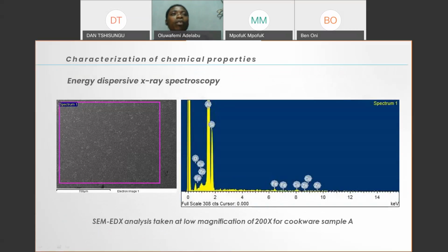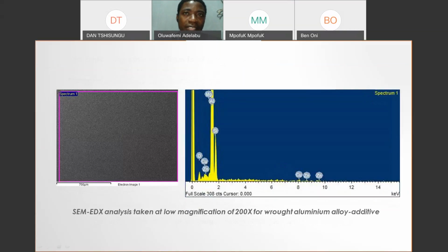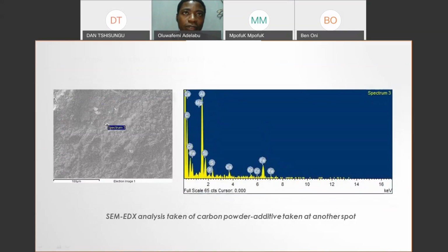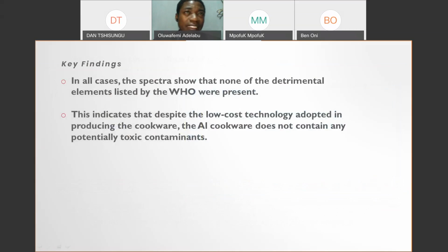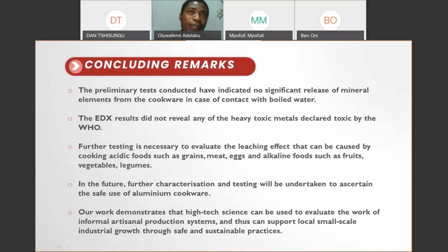All right. So we also did the characterization of chemical properties, and we did that for all the samples. Basically, in all cases, the spectra showed none of the detrimental elements listed by the WHO were present. And so this indicates that despite the low-cost technology adopted in producing the cookware, the aluminum cookware does not contain any potentially toxic contaminant. So our concluding remark is that the preliminary test indicated that no significant release of mineral element from the cookware was observed in case of contact with boiled water.